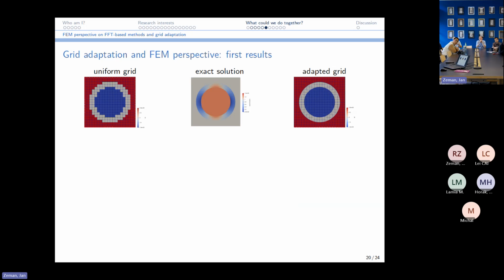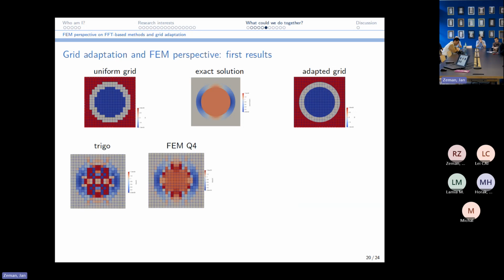within the shell. And if you do that with a traditional FFT-based method on a uniform grid using traditional trigonometric discretization, for a bad resolution, as we have here, you will get lots of oscillations and very bad results. If you use the FEM integration and discretization, you improve a bit. Okay, this is a very low resolution. So if you increase the resolution, you will converge to the solution, obviously. But if you have a very large domain, you cannot have a very good resolution on each of the constituents. So usually we're in this case.